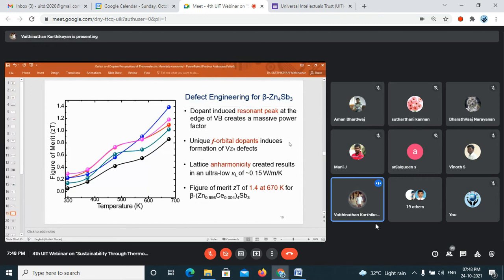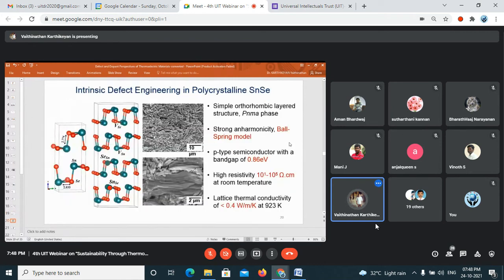Then we go for tin selenide, which is more interesting. Here, why I want to particularly show this material is that this is the peak material right now, which shows an efficiency, I mean the ZT, close to the peak. Unlike the chunk formation, here it is a layered arrangement. This gives another additional advantage like graphene and graphite: electrical conductivity and electron transport can be drastically high.